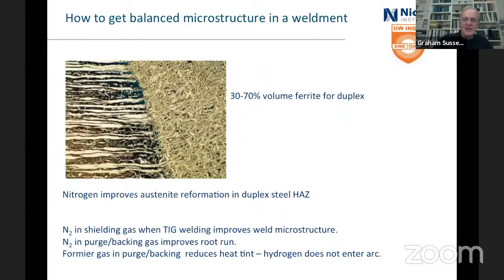This is just another way of saying that nitrogen is great stuff, but it's going to add one extra bit, and there's the weld, and that's the rolling, the structure. Nitrogen in the shielding gas, if you're using TIG, will give you a bit more austenite there. If you put too much in, then you'll get very much austenite, and it'll fail you. It'll fail all sorts of things. If you put it in the purge backing gas, then it's going to give an improvement in the corrosion resistance to the root run. But in Europe, people use Formier gas, which is a mixture of nitrogen and hydrogen, which reduces the heat tint, and the hydrogen doesn't enter into the arc because that's a backing gas.